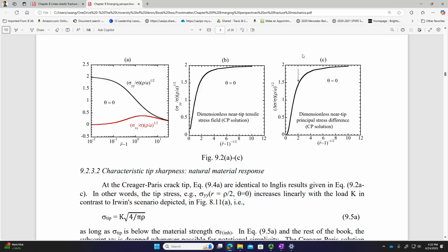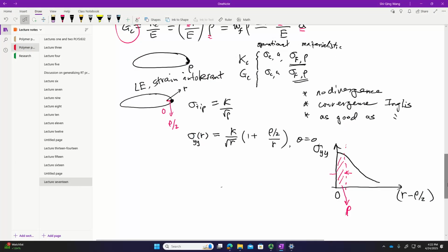That's the concept. All I'm trying to say is, look at the mathematics of it, you realize there is a region where stress is pretty high. Pretty high compared to the tip stress. And how big is that region? Let me casually say it's about 1/8 of rho. So at least 1/8 of rho will have high stress, which means you store high energy in that region.